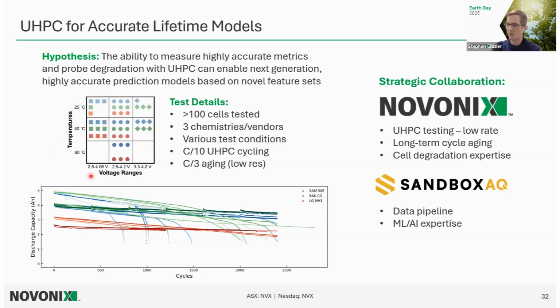And we did this between different SOC ranges, so really challenging a generalizable model, so that we're cutting out some of the failure mechanisms due to, say, the cathode here, where we're stopping the cell at 4.06 volts, not going into that last lattice contraction and the high reactivity level of the cathode, the full SOC range, and then this last SOC range where we cut out some of the silicon capacity, only discharging to 3.3 volts. So combining that with the different temperatures and different SOCs, this makes the cells fail very differently.